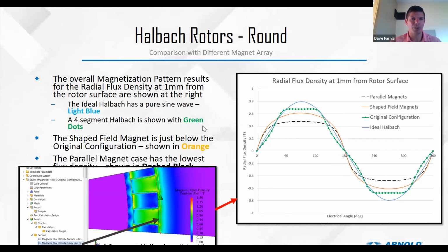Kind of the same with a round rotor. So if we take that same 4-segment Halbach pattern, model it in JMAG, I'm going to put a section line right above that rotor surface, look at the field, and compare it to, say, a standard parallel magnet pole, a non-Halbach configuration, which would be the dashed black. If we do a little bit of field shaping, let's say that Halbach-like configuration, we're going to get to orange. If we get to a 4-segment Halbach, dashed green, and an ideal Halbach in blue.